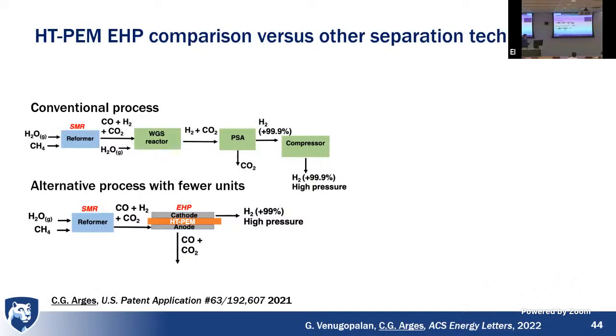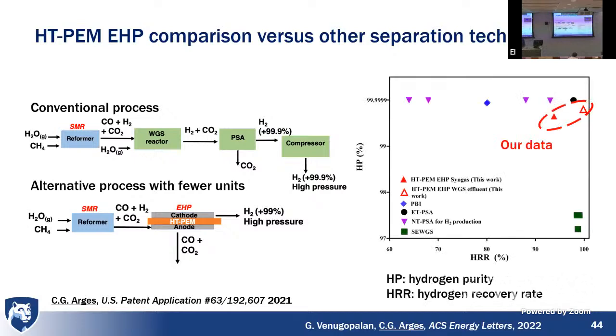I want to say here, if we look at a conventional process, normally how you deal with the CO, you can make further hydrogen through a water gas shift reactor after reforming methane. And then you use pressure swing absorption to make pure hydrogen, and then you'll compress it. But with this hydrogen pump, you could take this heavy CO mixture from a methane reformer, purify the hydrogen and pressurize the hydrogen at the same time. So you can simplify the process with this technology.